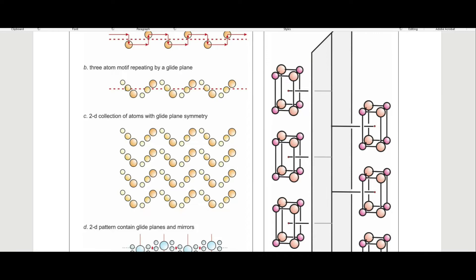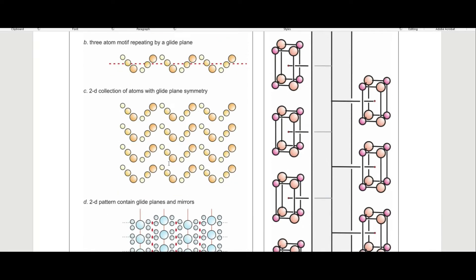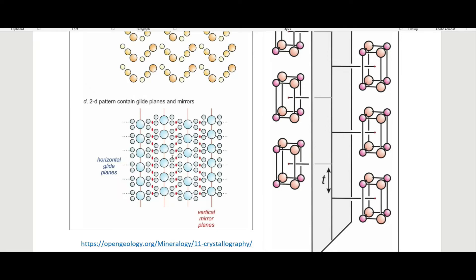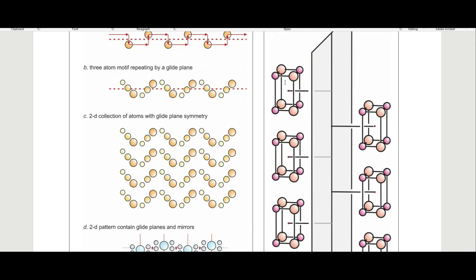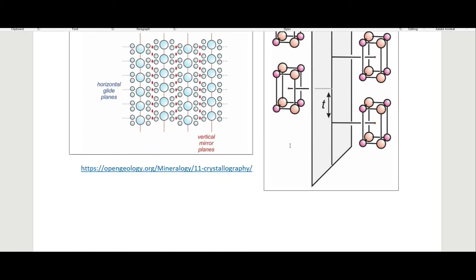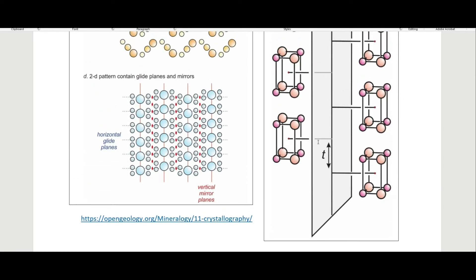Consider a three-atom motif with small, medium, and large atoms: you translate down by some fraction of the cell and then reflect, so that the large one ends up on this side and the small one on the other side. You can do this in 2D with complex-looking lattices, and also in three dimensions where you translate down and reflect across the middle line, then repeat — translating a fraction of a cell and reflecting. Those are the glide planes.